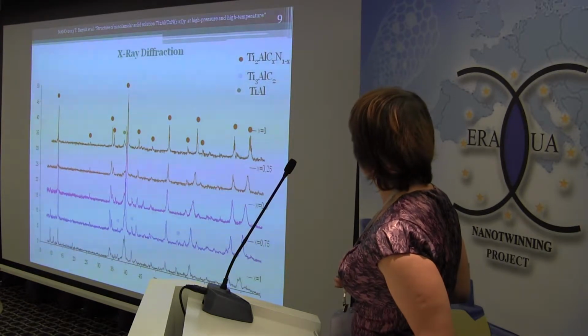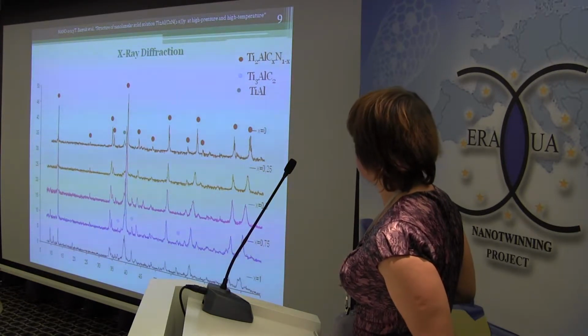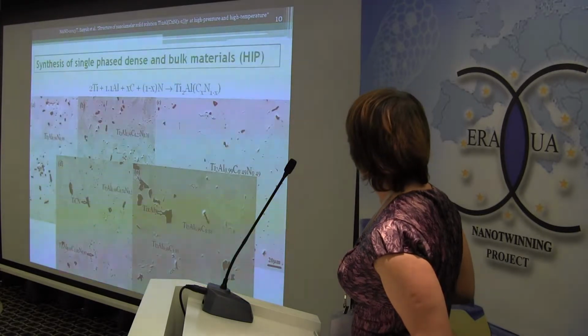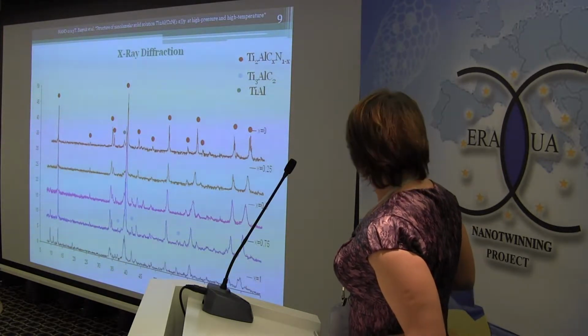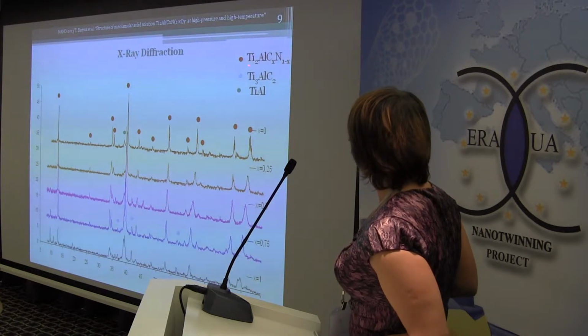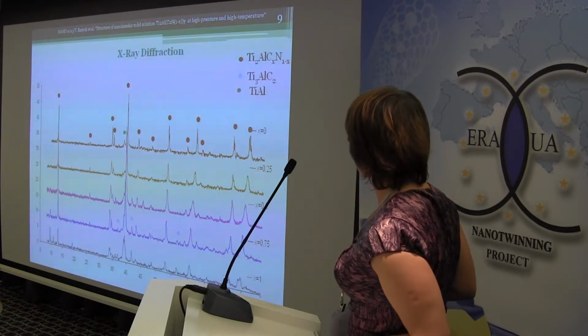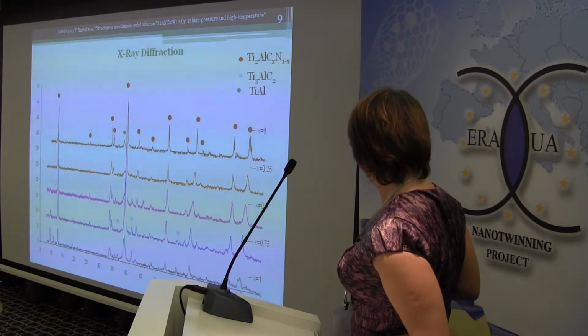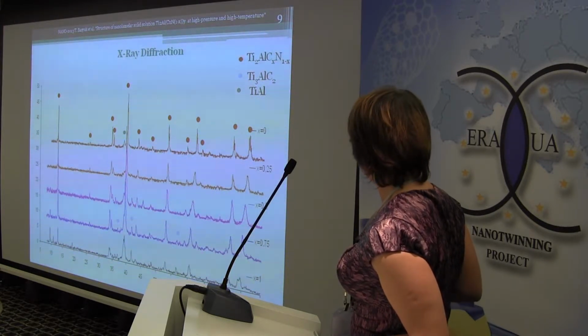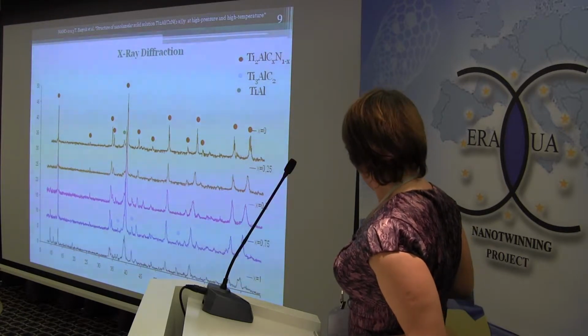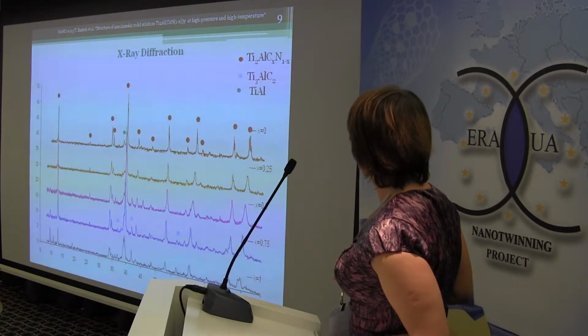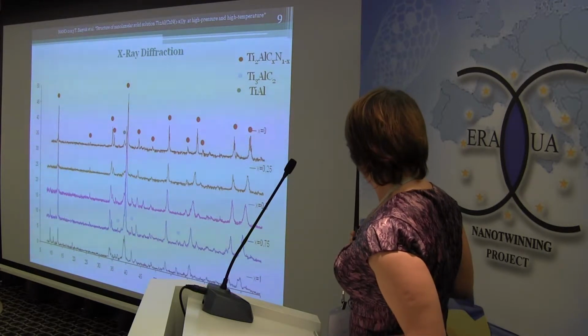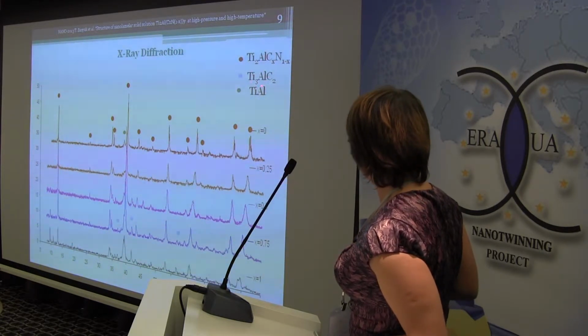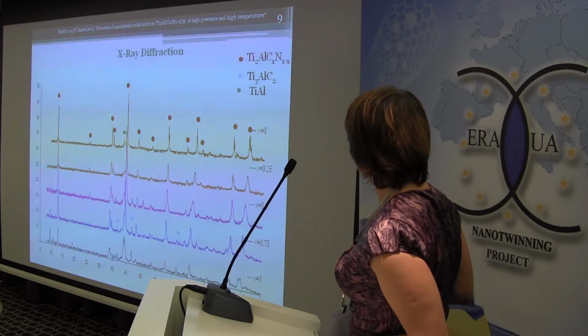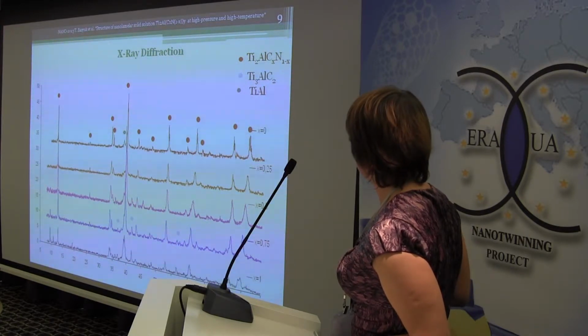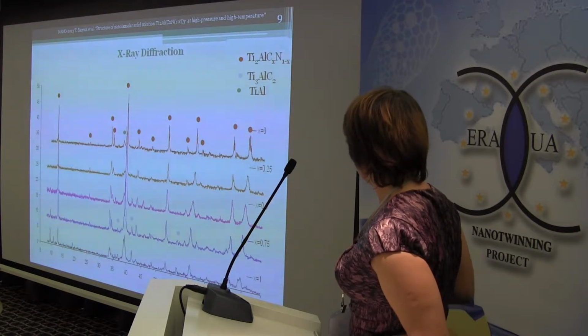Using X-ray powder diffraction analysis, we estimated that the main phase of our samples is the carbonitride solid solution. A small amount of titanium aluminide was found, near 4%, and some amount of 312 phase, and its amount increased with decreasing nitrogen content.